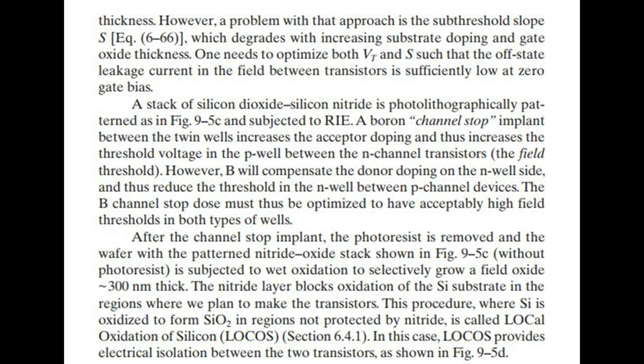However, B will compensate the donor doping on the N-well side, and thus reduce the threshold in the N-well between P-channel devices. The B-channel stop dose must thus be optimized to have acceptably high field thresholds in both types of wells. After the channel stop implant, the photoresist is removed and the wafer with the patterned nitride oxide stack shown